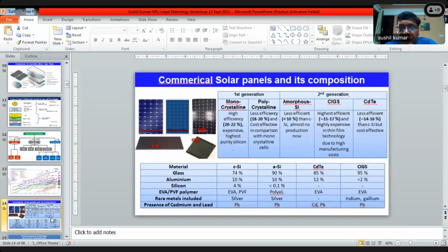As for the commercialized cells, as I mentioned, only the first generation and the second generation have commercial solar cells and module panels available. Like monocrystalline silicon and polycrystalline silicon in the first generation, in monocrystalline, efficiency from 20 to 22% is available, and it is because of the purity of the silicon that gives more efficiency. Polycrystalline is 18 to 20%. Amorphous silicon is a thin film solar cell. The growth process is entirely different for this.